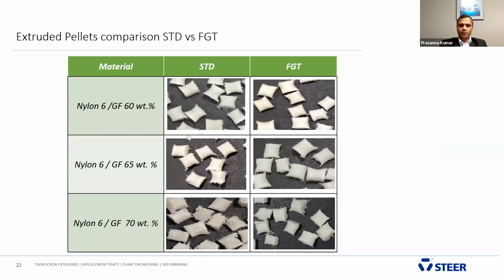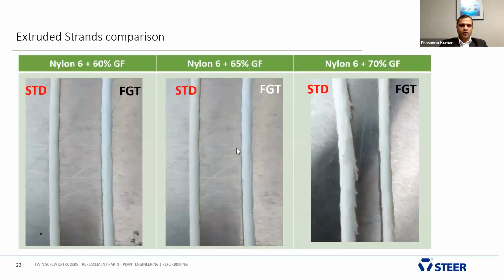And I'm just showing the picture of how the pellets look using standard geometry and FGT. You can see in the standard, the wetting of the glass fiber is not good with the polymer matrix, whereas in FGT, we got a much better wetting with the polymer. And this is the strand comparison for standard and FGT with various loading. So you can see at 70%, the standard has a very poor wettability of glass with the polymer matrix, whereas FGT provided a much better homogenized mixing as well as wetting.